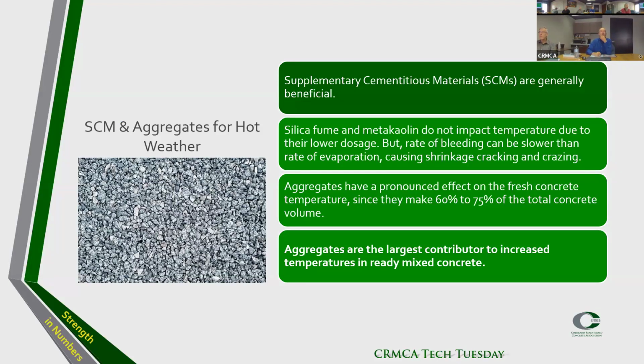Yeah, so SCMs, supplementary cementitious materials, they're generally beneficial, what we already saw for the strength development. Generally, silica fume, metakaolin, they do not really impact the temperature of concrete because of their low dosage. They're generally dosed up to 10% of the total cement content. But what we mentioned before, bleeding rates can be very slow for these mixtures and cause shrinkage, crack, and crazing.